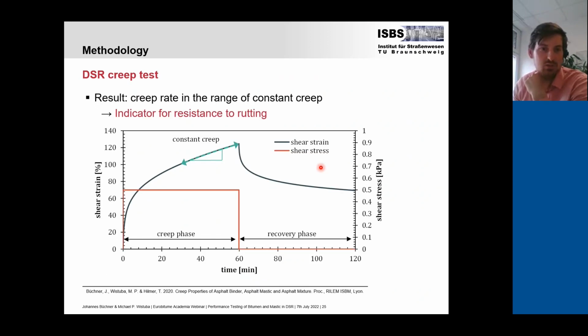For the creep test, we also looked at the MSCR, which is available in the European standard, but we also looked at the extended creep test, where we extended the creep phase to 1 hour. You can see here a creep phase of 1 hour with a constant shear stress of 0.5 kilopascal. We added a recovery phase of 1 hour with a shear stress of 0, and we can clearly see the shear strain, which evolves here, reaches a quasi-linear phase, constant creep, and then we can already see the recovery in the second part.